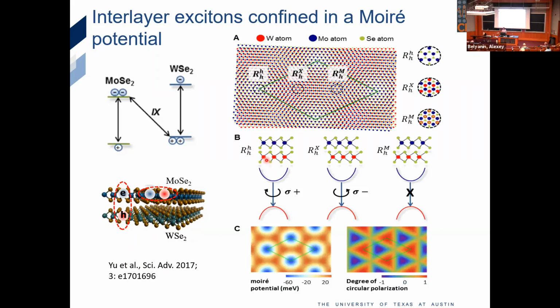Another thing that happens is that we're going to come back to these three high symmetry points. I want to discuss selection rules again. So now remember, I said there's a K valley and K prime valley in monolayer. That concept is still valid in the heterostructure. But it's much more complicated if I only look at transitions in one valley. I now have three different sites, A, B, C sites. If I can put an electron hole pair in one location, they would have different selection rules. In one location, they will have sigma plus. In a different location, they will have sigma minus. In the third location, they actually have a dipole that's perpendicular to the 2D plane that does not couple to plane waves shining on the 2D material easily.